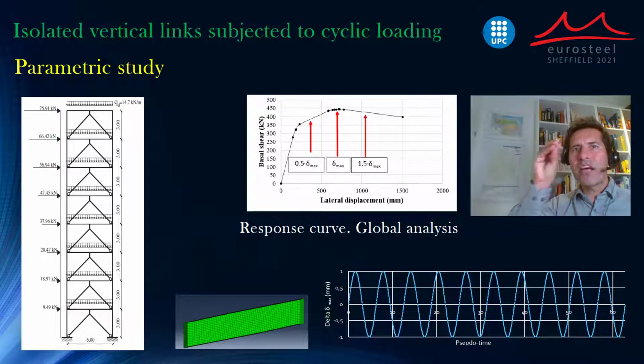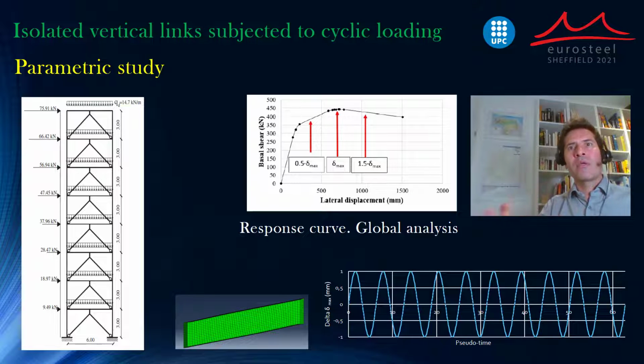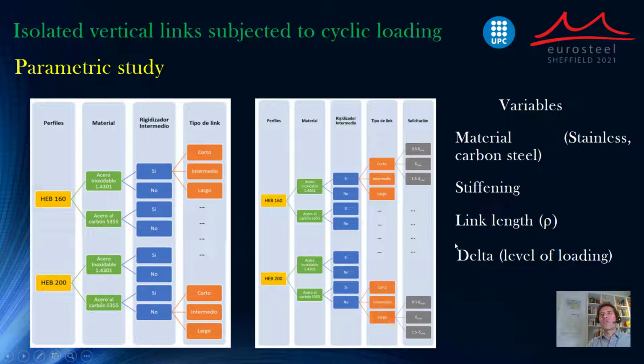So let's keep in mind these 3 values of displacement of the system according to the global analysis. With these values, we provide cycles of loading to the link in a detailed model, and this link will be subjected to a delta which is related to 0.5 delta or 1.5. So we developed a parametric study in which variables such as material, stiffening, link length, and delta, which is the level of loading, and with a profuse variation, we can have some results.